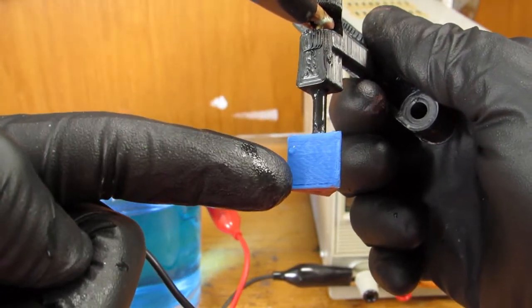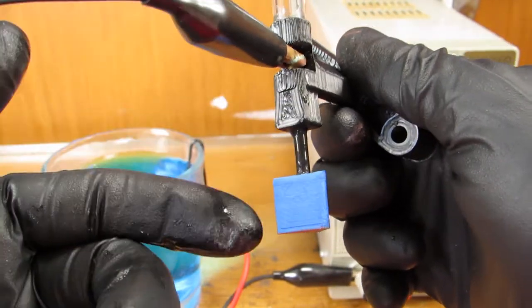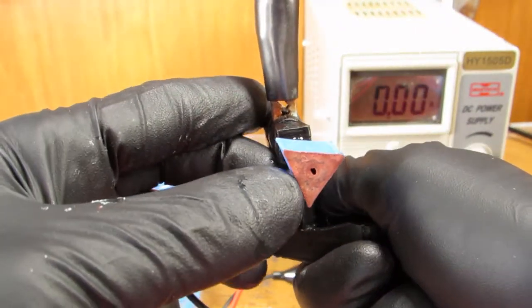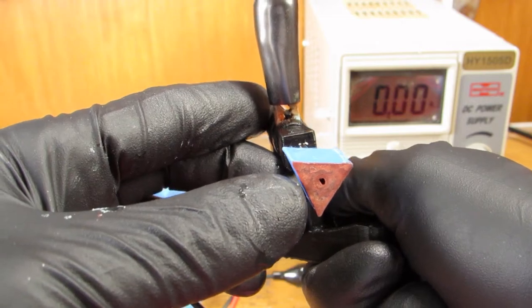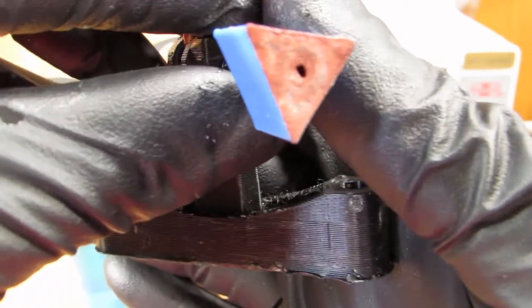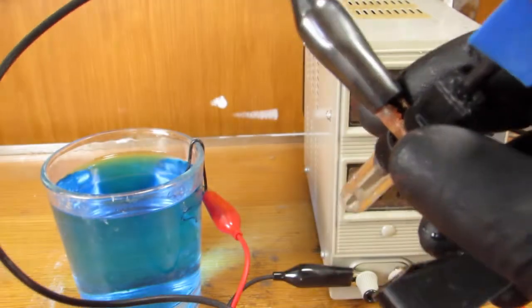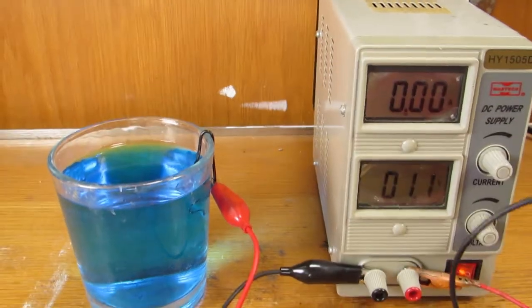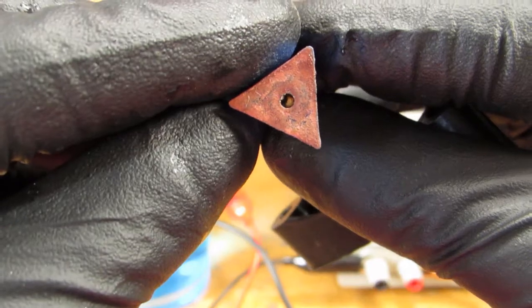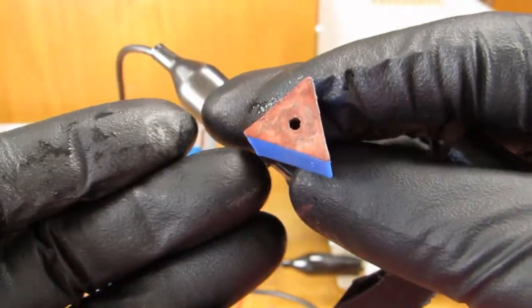So there's a nice shot for you. Because of how this actually works, we're going to be able to get pretty high current densities at our machining area but very low current densities distal from the machining area, as everything else is well insulated and it's not even made out of metal. And then we've got a very conductive metal as our machining face here. You can see that the copper has partially occluded our electrolyte source, so the business end of the electrode that actually pumps the fluid into the inter-electrode gap has been partially obscured here. But I can actually just take any random tool and bore out the center there, so you can see that actually looks pretty decent.